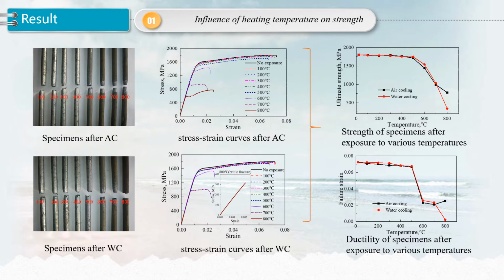The left picture shows the specimen after a tensile test. The middle 2 pictures illustrate the stress strain curves obtained from tests, and the right picture summarizes how strength and ductility vary with temperature. As can be seen, for temperature below 500 degrees centigrade, only slight reduction of strength was found.